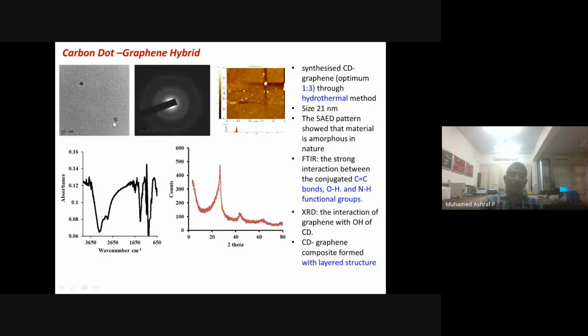You can see the carbon dot is a very small molecule, and this shows that there are no inorganics, only organic carbon. Otherwise we would see some crystalline structures. This is the FTIR, and the lowest one is the XRD structure. FTIR showed that the C=C bond system of the carbon dot interacted with the graphene, and it is like a layered structure.